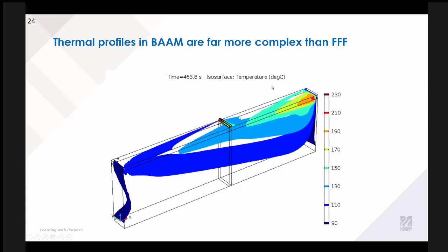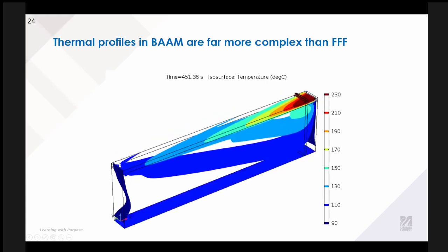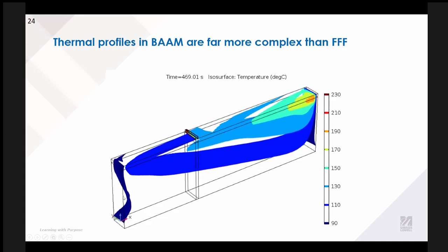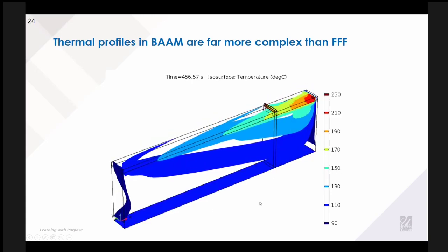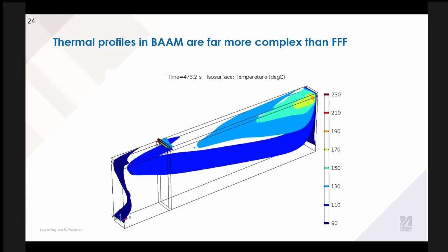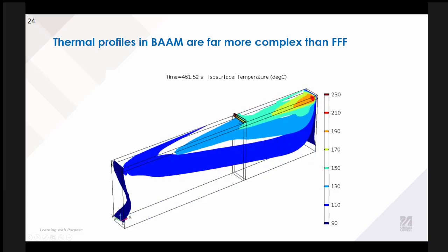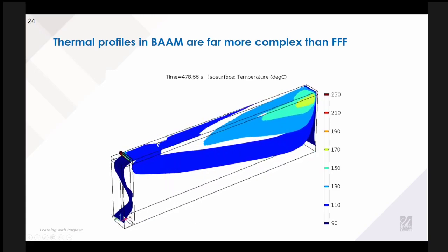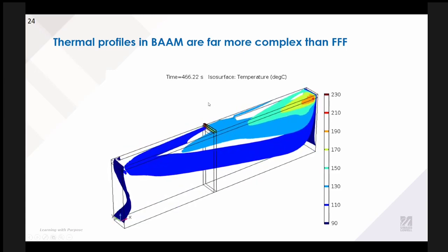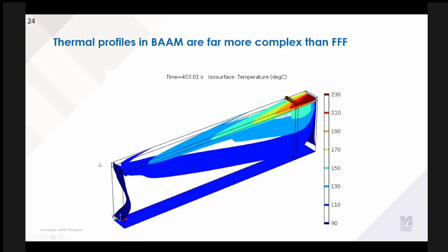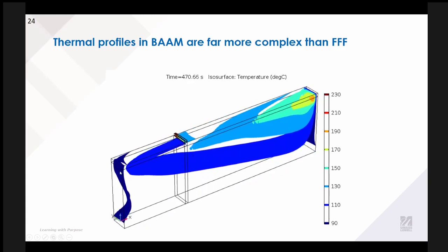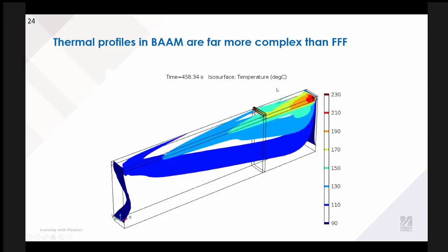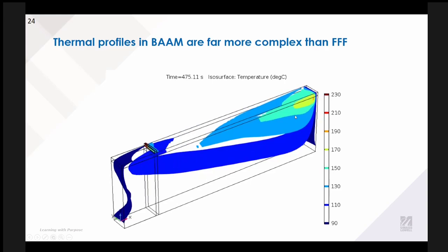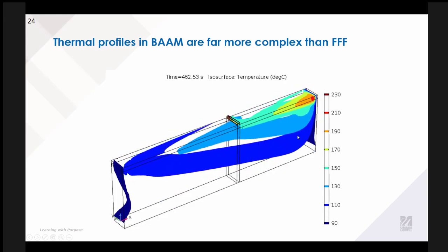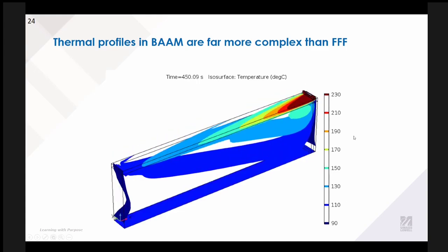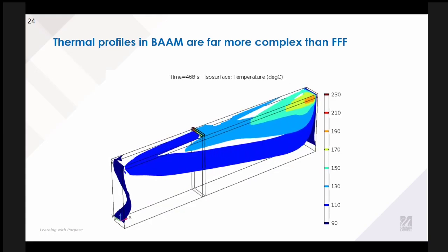Another thing that I wanted to just highlight is this is showing there isn't material being extruded during that part. The iso surfaces that evolve during BAM are really complicated, because these are big structures that are getting rid of heat in a bunch of different ways. There are simplifications that we can make at smaller scales that really start to not be valid in BAM. One of the other things that really starts to appear is the importance of tool paths. You can see in all of these where we're printing and then returning and then printing another layer and returning. And you can see that the side that is printed last is staying hotter for longer from the iso surfaces. So there's a lot to be thinking about and a lot to be looking at here.